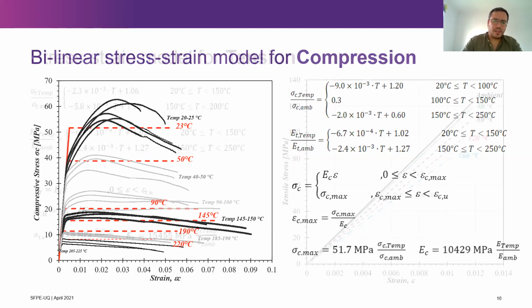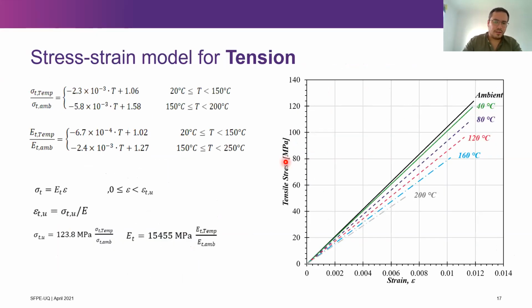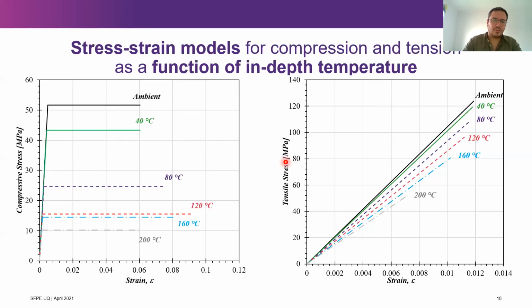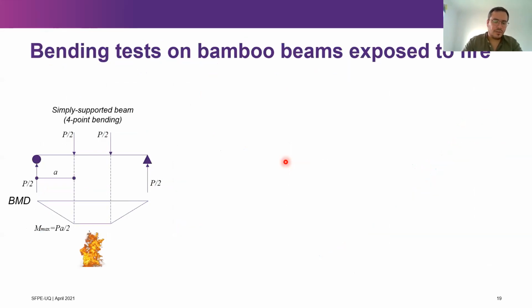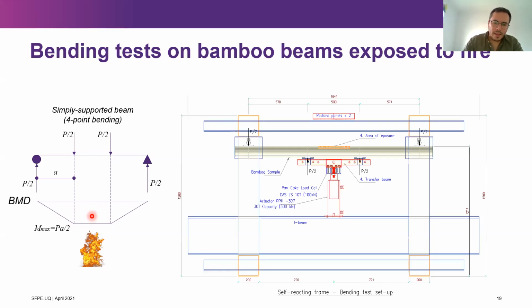So again, we describe the performance of bamboo with different equations. Those equations were functions of temperature, and with these constitutive stress strain models, we moved to the next stage, which was the analysis of bending specimens exposed to fire. In order to test those elements, we again decided to go for the simplest scenario, which is a simply supported beam loaded in 4-point bending, right? So obviously you have the maximum bending moment in the central third of the beam, and we expose that part to fire, right? But conducting fire experiments is not an easy task.